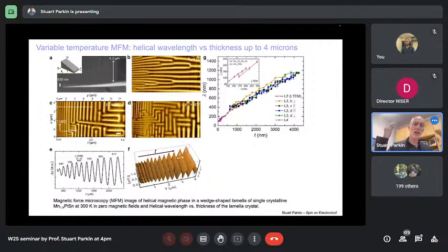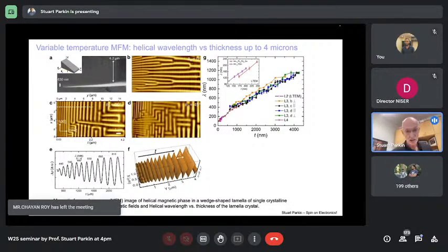So basically, if we apply a big enough field, we will see a uniformly magnetized state. As we reduce the field, we'll see skyrmions, anti-skyrmions, and then we see this spiral state. And it turns out that the helical state in this system in which we see anti-skyrmions, the direction of that helical state is only along one of two perpendicular crystallographic axes. And we can change the orientation of the helical spiral by applying in-plane magnetic fields.